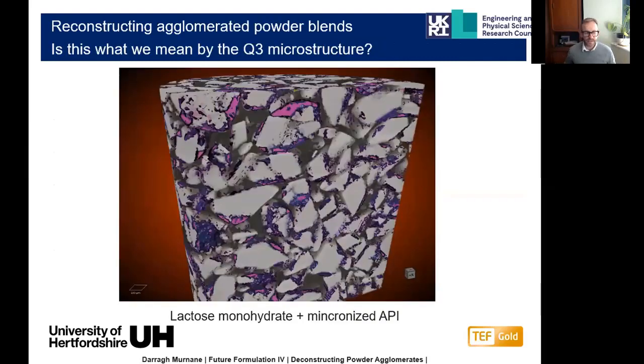So when we start to think about what the microstructure is in the formulation, we can see we're now able to build up three-dimensional images. We can look to see the particle size distributions. We can see things like porosity of powder, density of the powder bed. We can see location of the drug distribution throughout the blend and start to really investigate what that microstructure of a powder would be and build that into our performance models, whether it's aerosolization or blending performance, content uniformity performance, to really start to inform ourselves how those materials are going to behave throughout the formulation process.